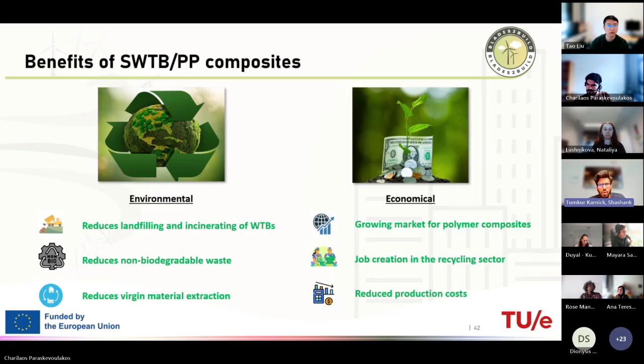and also this has actual potential to be reused or recycled into new polymer composites, which eventually reduces the non-biodegradable waste which arises because of these wind turbine blades. And as I mentioned earlier, it can also reduce the virgin material extraction, because as I told you earlier, it can actually substitute virgin glass fibers by around 10 to 15%. So this is also one of the environmental benefits.